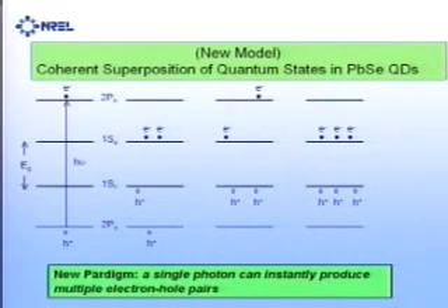So energetically, this is the band gap, and we can show that the transition from 2p of the hole level to 2p of the electron is equivalent to having 3 excitons at the 1s levels, or also a bi-exciton, one of which has an excited hole or an excited electron. So you have this produced instantly, and then you will have oscillations or quantum beats between these states.